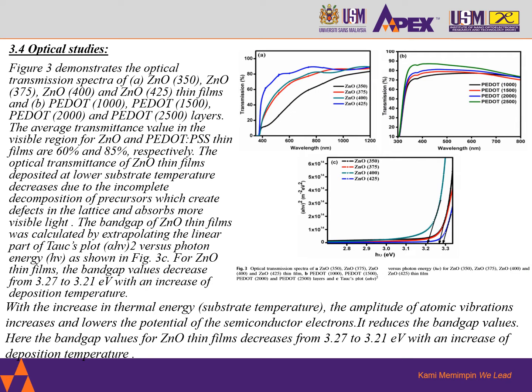Now the optical studies. Figure 3 demonstrates the optical transmission spectra of the zinc oxide 350, 375, 400 and 425 thin films and the PEDOT:PSS 1000, 1500, 2000 and 2500 layers. The average transmittance value in the visible region for zinc oxide and PEDOT:PSS thin films is 60% and 85% respectively. The optical transmittance of zinc oxide thin films deposited at lower substrate temperature decreases due to the incomplete decomposition of precursors, which creates defects in the lattice and absorbs more visible light.